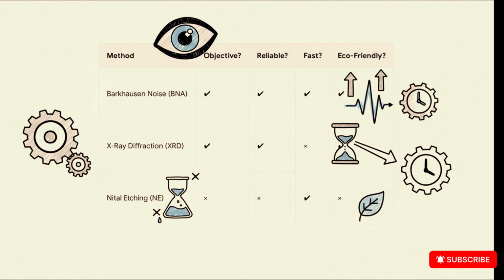So, finding this invisible threat takes some pretty serious tech. The old school way, called nital etching, literally involved dipping the gear in acid. I mean, it was messy, unreliable, and definitely not good for the environment. Today, thankfully, manufacturers use advanced methods that don't destroy the part. You've got X-ray diffraction, which can measure stress, but it's pretty slow. A really top-tier method these days is called Barkhausen noise analysis, or BNA. The great thing about it is that it's objective, it's reliable, it's fast, and it's clean. That makes it perfect for checking every single critical gear coming off a production line.